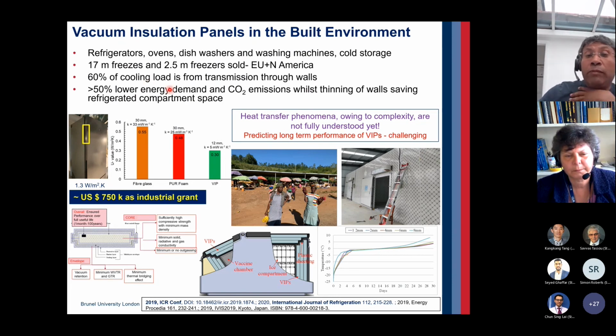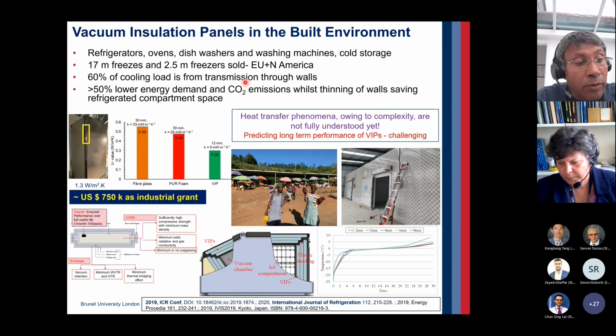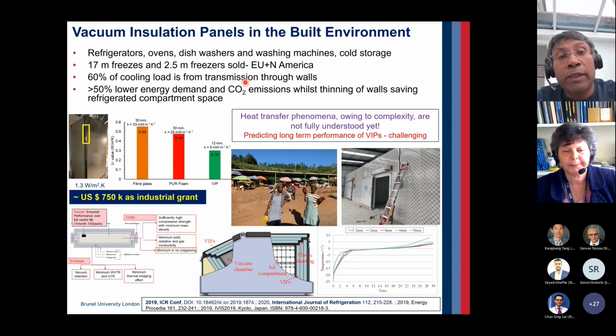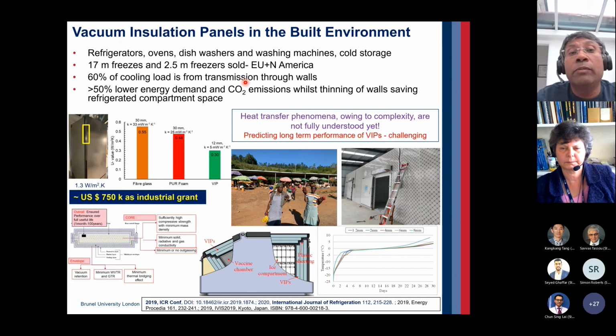The reason is that we're selling around the world a huge amount of refrigerators and freezers every year. Within only the European Union and North America, 17 million fridges and 2.5 million freezers are sold every year. They are responsible for a huge amount of emissions, depending on which source of power they are using. We've shown through our research that 60% of the cooling load is transmitted through the walls, which can be saved. If insulated by VIPs, we could save CO2 emissions by reducing the energy demand by greater than 50%. And by introducing more thermally resistant insulation in the form of VIPs, we could also make space within the refrigerated compartments, allowing the freezers to be more attractive to customers.